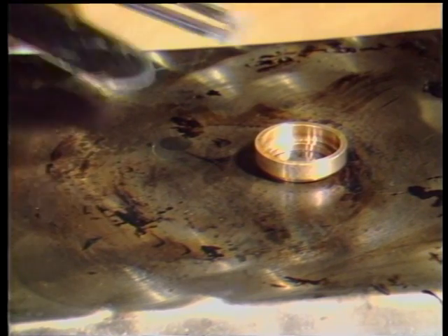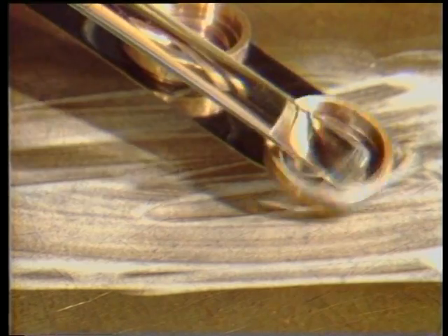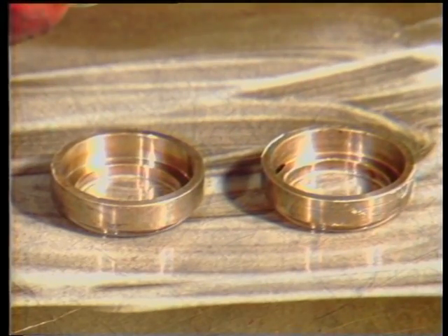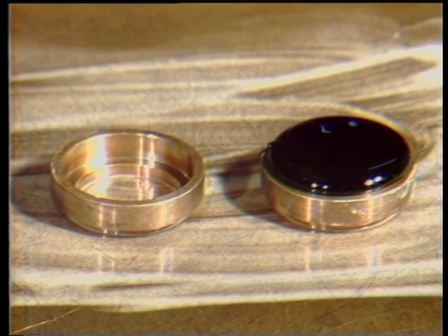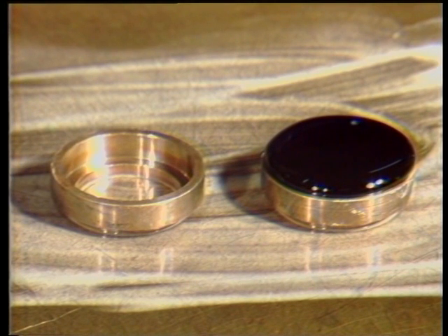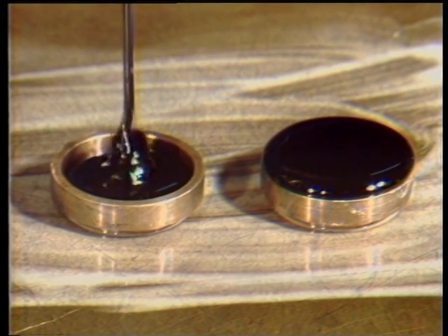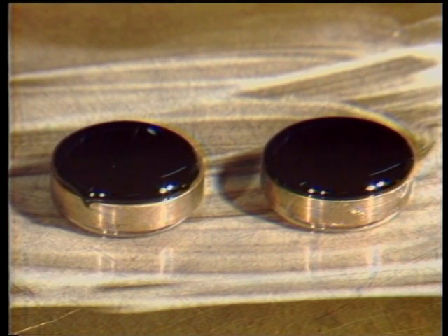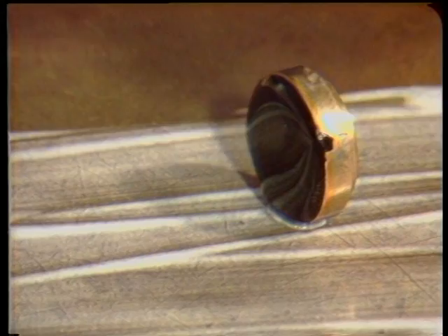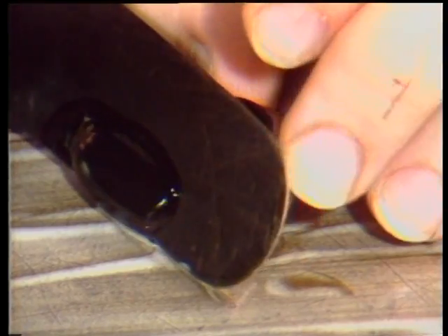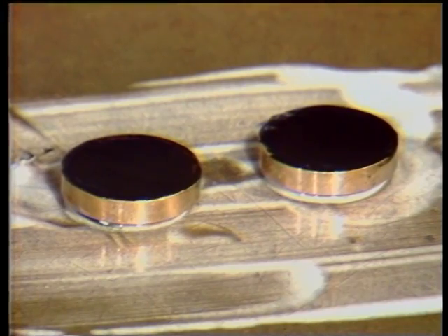Heat the 2 rings to approximately the same temperature as the sample and place them on the metal plate. Then, without delay, fill the rings with the sample so that there will be an excess above the top of each ring. Allow the filled rings to cool for 30 minutes at room temperature. Remove any excess bitumen by using a heated spatula so that the test specimens are level with the top of the ring. Start the test not less than 10 minutes and not more than 8 hours after leveling the specimens.